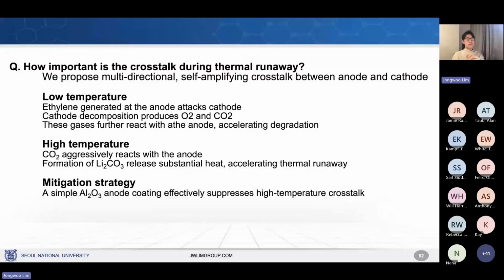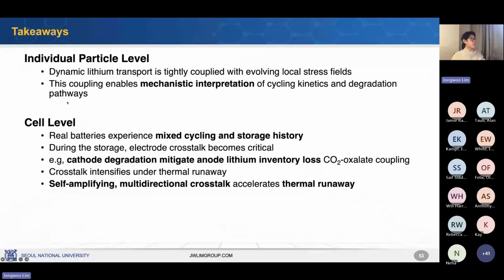So I want to just have one slide to summarize my work. So we investigate at the individual particle level that the lithium diffusion is not simply smooth. There's always a stress transformation. At the electrode level, interparticle communication matters for the gas evolution. At the cell level, cathode and anode, they are communicating even more, complicating calendar aging and making the thermal runaway more severe.